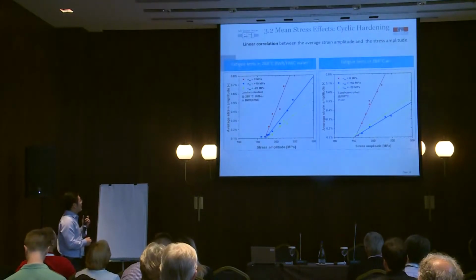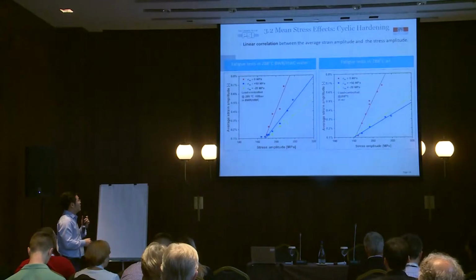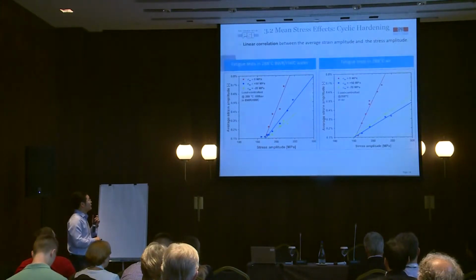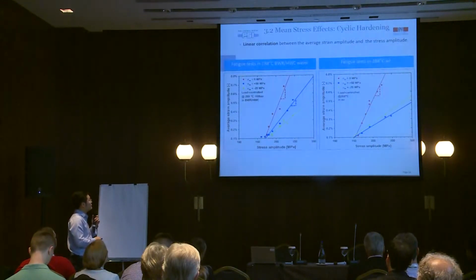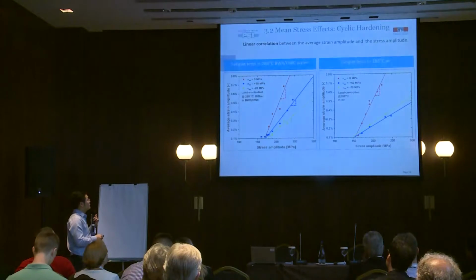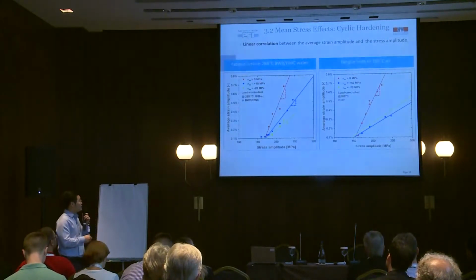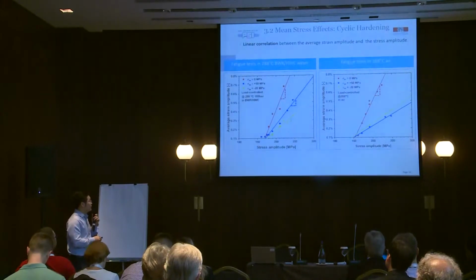If we plot the average strain amplitude corresponding to the stress amplitude, we found that there is a linear correlation between these two parameters. And if we take a look at the slope of different mean stress conditions, we found that the slope with mean stress is smaller than without mean stress, which means the mean stress has hardened the material. If we compare the slope in two different environments,